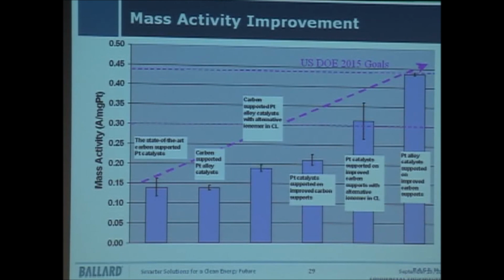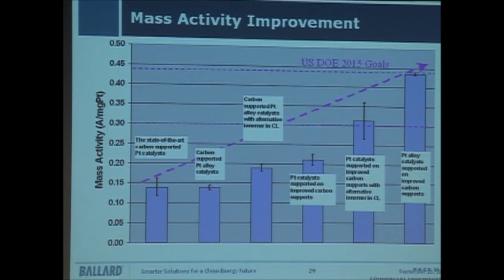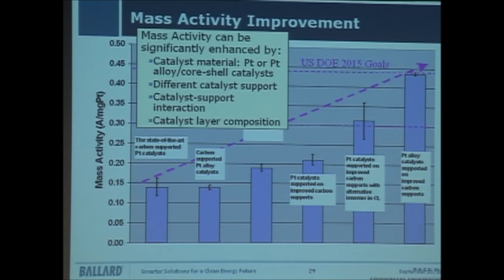For performance, with existing technology in combination of many ways, like alloy catalyst, different supports, even changing the ionomer in the catalyst layer, or a combination of all of them, we do demonstrate in small scale tests that we can get the mass activity to reach the DOE 2015 goal. This is achieved by a combination of many ways, not only catalyst material but also the catalyst support. Choosing the catalyst material is important, but understanding their interaction is also key to durability improvement. And of course, catalyst layer composition is extremely important to maintain or enhance your activity.